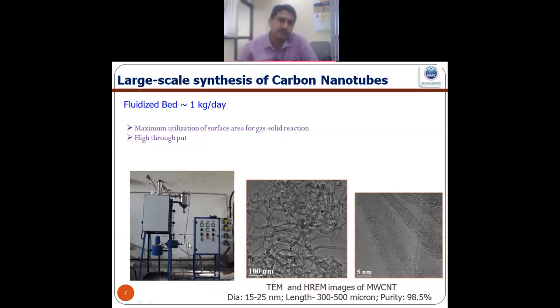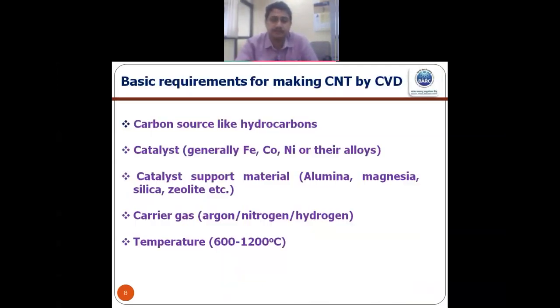Here in the leftmost figure you can see a fluidized bed furnace which has been designed and fabricated at BARC, which can produce almost a kg of carbon nanotube per day. You can see the TEM images and high resolution TEM images of the product, where you can count the number of walls also. And this carbon nanotube is of the purity of 98.5%.